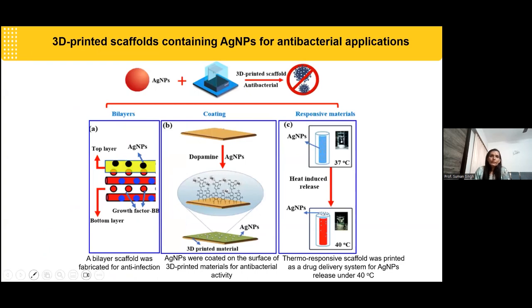This is another example where silver nanoparticles have been used for antibacterial applications, but in association with scaffolds. For example, in part A, in the form of layers, the silver nanoparticles have been embedded in this 3D printed structure and studied for antibacterial activity. Of course, silver is known for its antibacterial activities, but the moment you make composites, there must be some change, whether positive or negative, in its antibacterial activity.